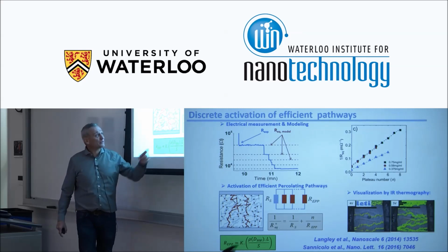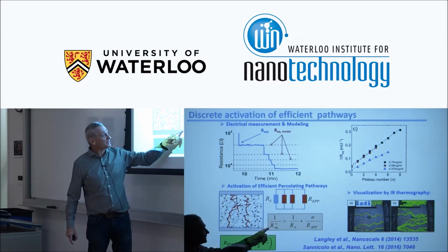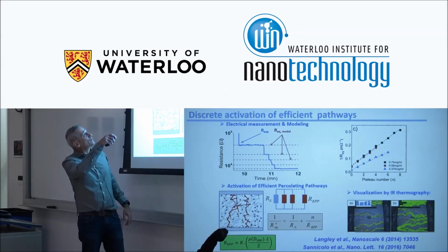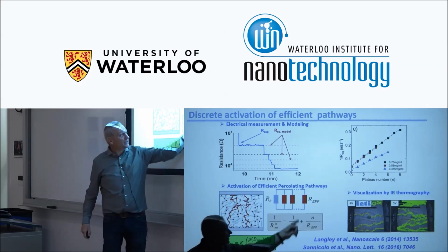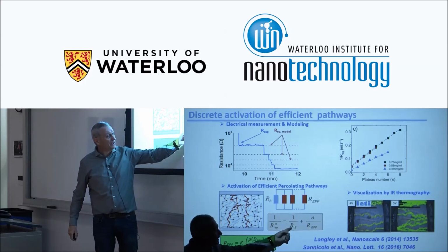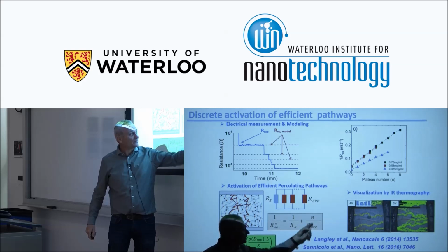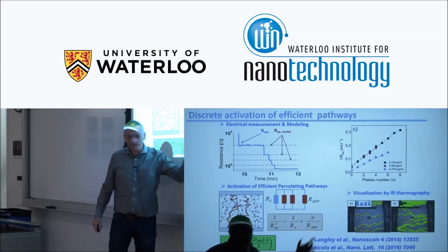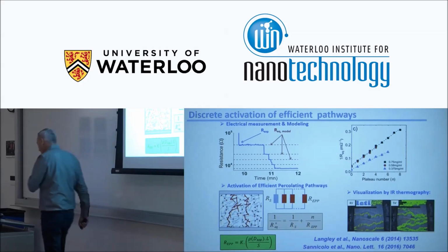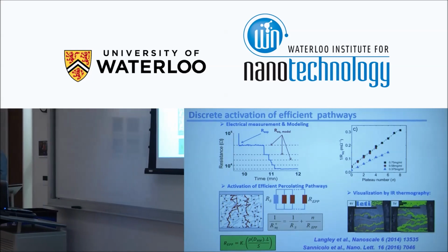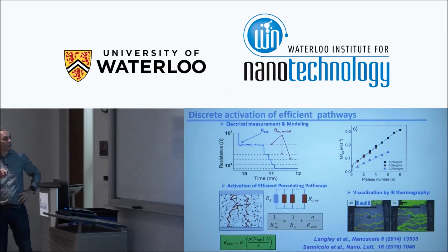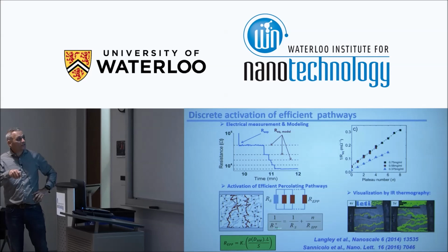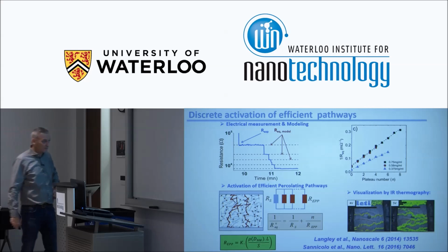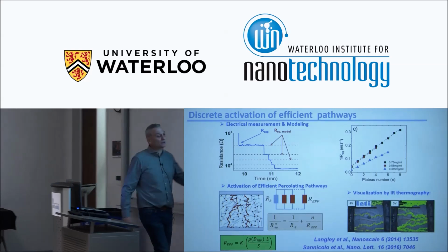So that means the inverse of the equivalent resistance after n plateaus like this could be the inverse of the initial resistance, which was very high, plus n times 1 divided by the resistance of an efficient percolating pathway. And if we plot, for example, 1 over the resistance versus the number of plateaus we observe, experimentally it fits rather well. We have a linear correlation, that's cool. The point is how we can